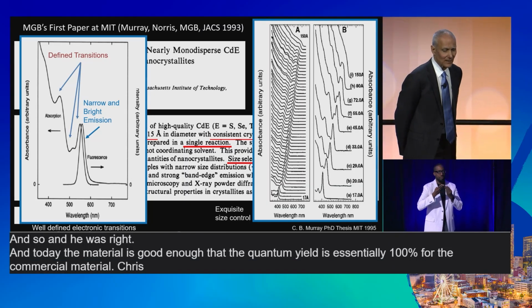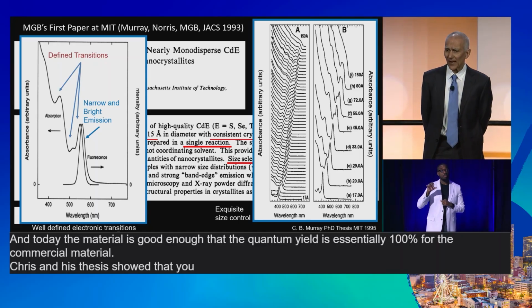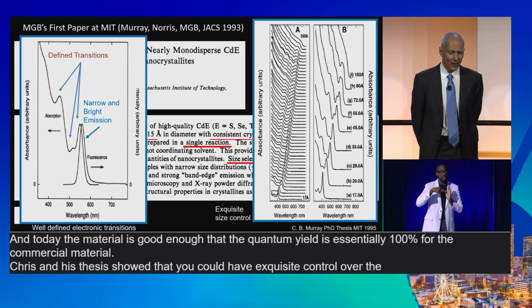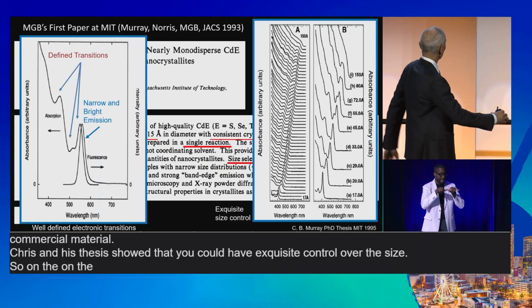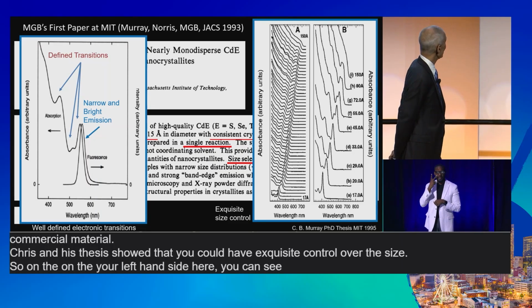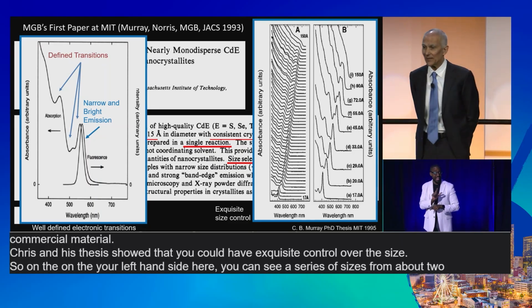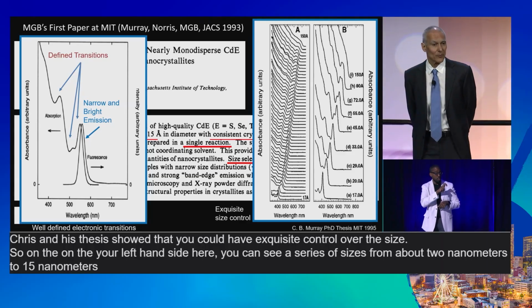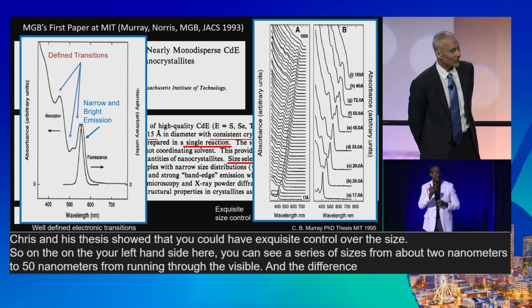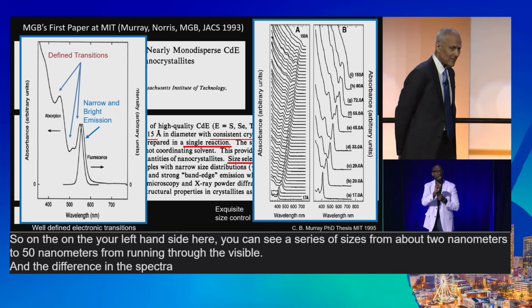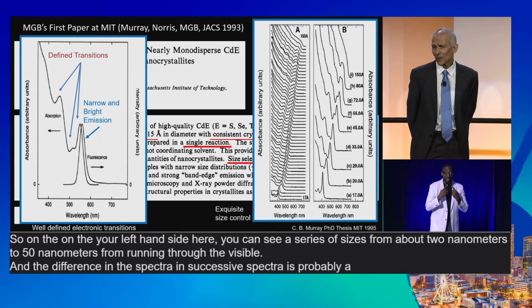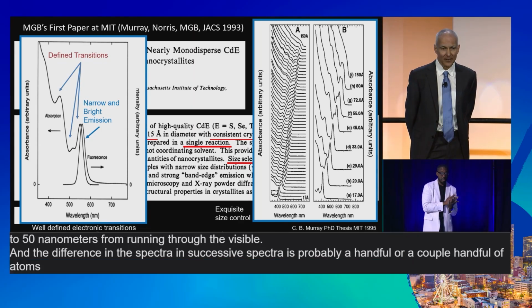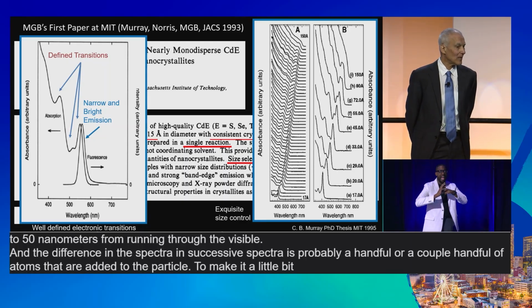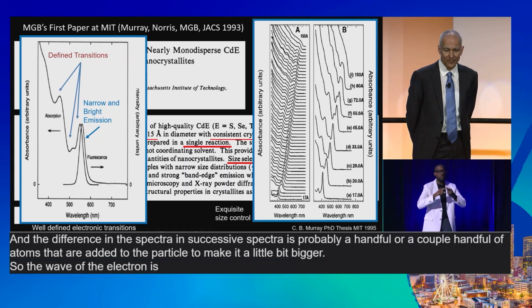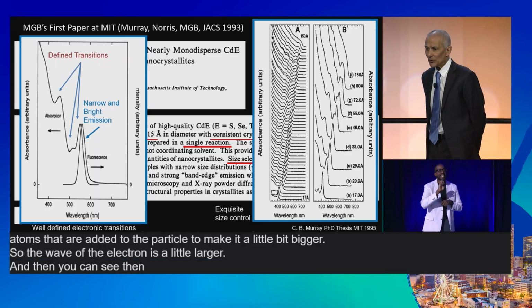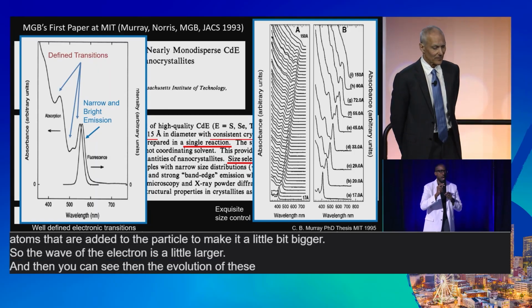Chris, in his thesis, showed that you could have exquisite control over the size. So on your left-hand side here, you can see a series of sizes from about 2 nanometers to 15 nanometers running through the visible. And the difference in successive spectra is probably a handful or a couple handful of atoms that are added to the particle to make it a little bit bigger, so the wave of the electron is a little larger. And then you can see the evolution of these harmonics as a function of size.